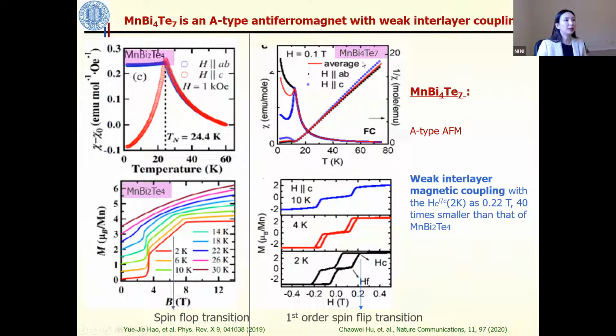Okay, so after we got single crystals, now let's take a look at the magnetic properties. Here is the magnetic property of the 124. As you can see, we have a spin flop transition here. And this is a comparison with the magnetic property of the 147. You can clearly see that the 147 does not have this so-called spin flop transition, but now you have a first order spin flip transition, and the saturation field is just 0.22 Tesla, which is almost 40 times smaller than that of the 124 compound. This actually suggests the success of our material design strategy here.